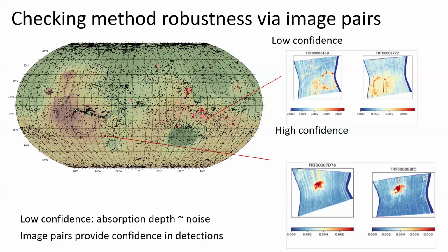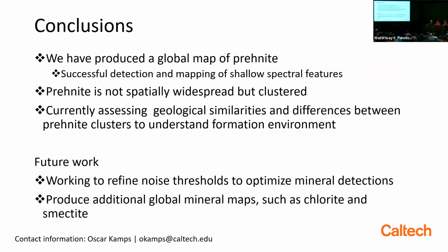But in the ones with low confidence, we see a spatial correlation around the crater rim, but there is also quite some noise in the data, which you can see as high values along the column. So just based on the depth values, it's hard to distinguish between noise and a spectral feature. That's what we're still working on, to see if we can build a better signal-to-noise ratio to better identify whether we are looking at a feature or noise in the data. Next slide, please. 30 seconds. Oh, great.